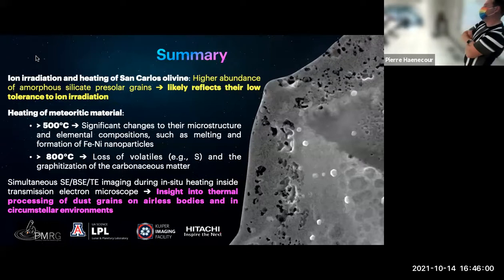One of the things that we are going to do, as soon as we get the nanoSIMS installed, is try to combine this with isotopic variation. We know that when you heat a sample, I didn't show you an example, but we see particles shrink, and it's likely due to loss of water. So hydrogen that was trapped in the sample, you basically shrink-dry the phyllosilicate, and you lose all the water that's trapped in it. But there are very few studies that show how hydrogen isotopes vary with temperature. So one of the things we want to do is compare the evolution of hydrogen isotopes as you progressively heat the sample.